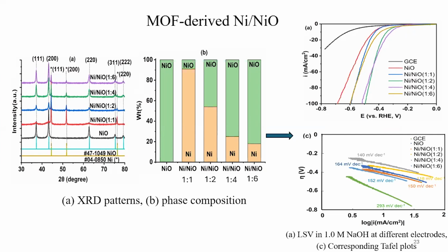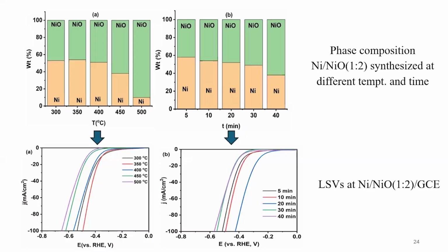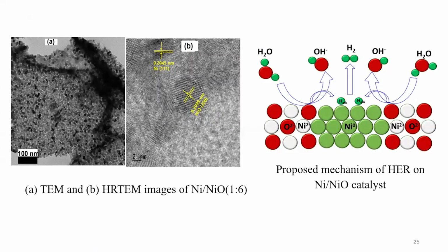And the same trend happened when we investigated the influence of annealing temperature and annealing time. So it suggests that there is a suitable ratio of nickel and nickel oxide within the sample to give the best performance of HER. And we propose that the metal and nickel oxide in the material facilitate the forming of hydrogen. So it facilitates the adsorption of water on the surface, and it also facilitates the combination of H plus to form hydrogen gas.